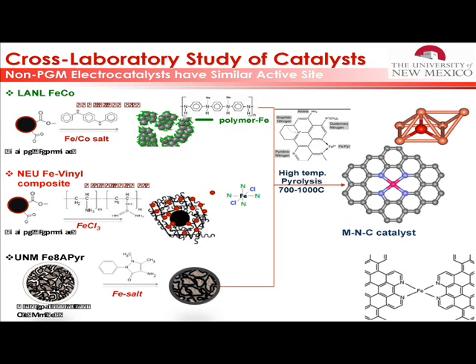Here is my slide. I think that pores contribute through edge defects. But edge defects of nitrogen are not the only defects that participate in the catalytic activity. In-plane defects are also prevalent because in our catalyst we have way more in-plane surface exposed, so of course there is defective surface. But defective surface only cannot explain the process.